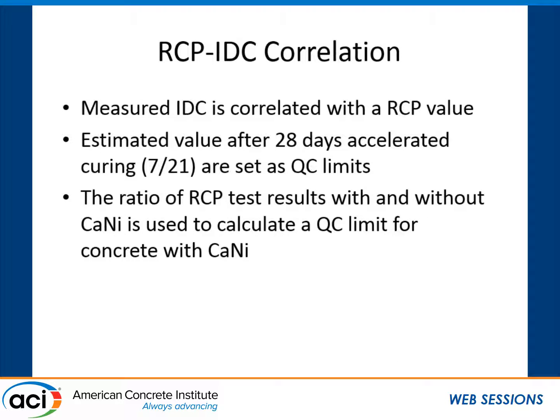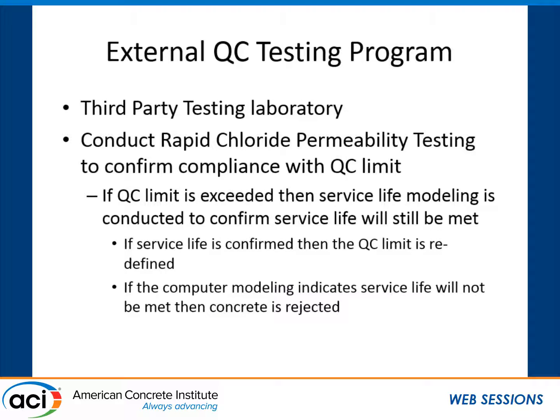And again, I fully agree with Ramon. The best way on this RCP is to do it at the regular 28 days, but also with the accelerated: 7 days of normal moist curing at 73 degrees, and then 21 days of accelerated curing at 100 degrees. This is something very typical of what Virginia DOT would be doing. And then in this project, the testing itself would go off to third-party laboratories. I think there are laboratories up in Quebec and others that would be running tests. And those limits would be coming down both in RCP as well as in some transport tests periodically.